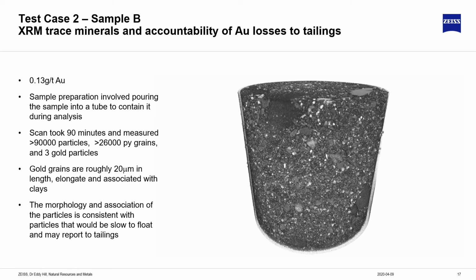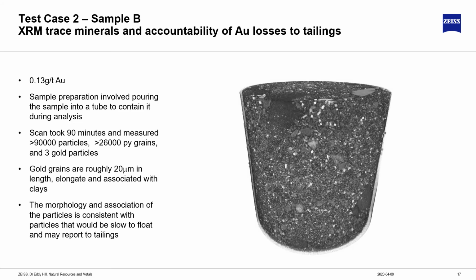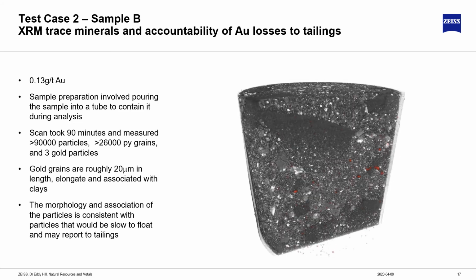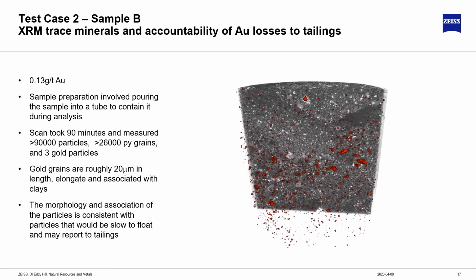What we found is that the gold grains that reported to the tailings are roughly 20 microns in size. They're elongate and associated with clays. Now, these clays were likely removed during the mechanical sample preparation for the 2D analysis when we prepared the metallographic plugs. The morphology and particles here are consistent with particles that would be slow to float, and therefore it is believed that due to the kinetics of the process, they were missed, and this is why they report to the tailings.